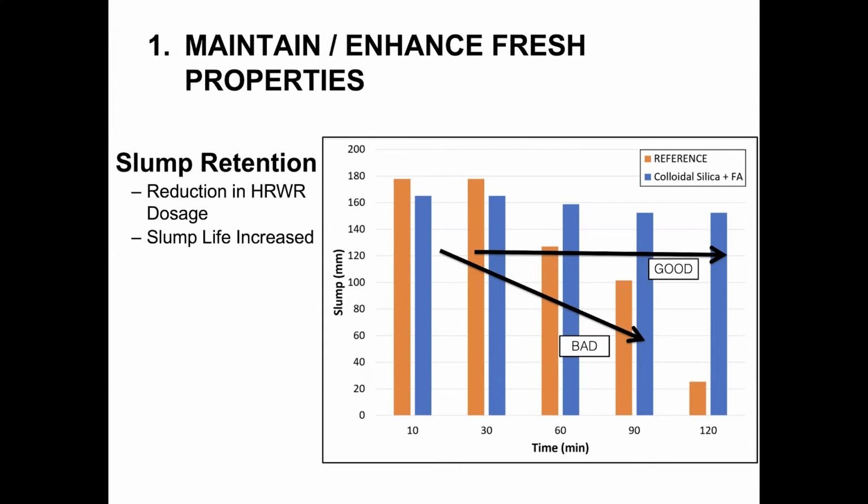Well, one of the main things that I saw the benefit in the field, first and foremost, as a concrete pumper, was even though specification products does not claim it to be a viscosity modifying admixture because it's not labeled as such, it certainly acts like it. So we saw reduced pumping pressures of almost 100 bar on average between like mixes and then a mix with the internal cure mechanism of the E5. So as you know, when you're pumping, it's that creaminess of the cement paste. Usually the higher the cement paste goes, the more a pump likes it. That's why it's so easy for a grout without a lot of large aggregate to be pumped.